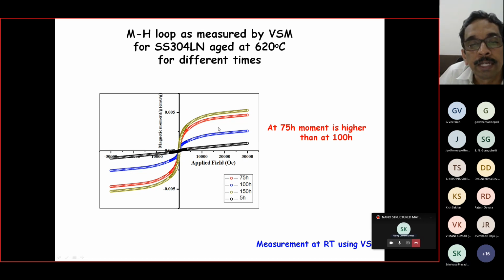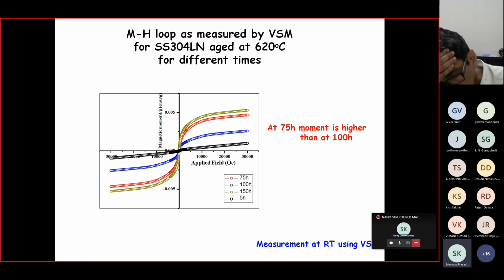Basically, we are trying to cycle a material from zero field to the highest field possible and again come back, and then there is a sort of hysteresis. So we try to do the hysteresis or MH loop for different times. I have aged this sample. Aged means I have kept it at 620 degrees centigrade for different times. Okay, why 620? Because I think this was a project funded by the Department of Atomic Energy where they are using these stainless steel pipes for their hot water pipes or something like that, where the temperatures are estimated to be 600 to 650 degrees centigrade.